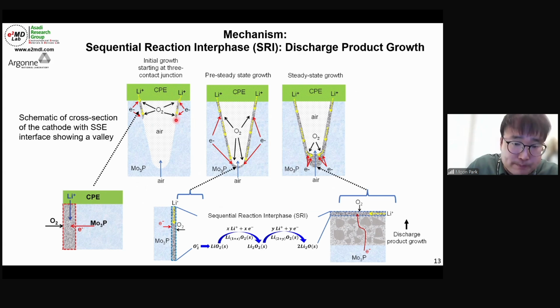It starts to grow on the surface of the cathode, and it grows and grows down to the bottom of the valley. Larry and Mohammad thought that once they fill and cover all the surface, it reaches a steady state. For example, from 0 to 15 minutes, and after 15 minutes it is in steady state. That means the lithium peroxide and superoxide still form, but once they form, this reaction is very favorable and very fast, because lithium conduction and electron transfer are very favorable. So the formation of lithia was facilitated.